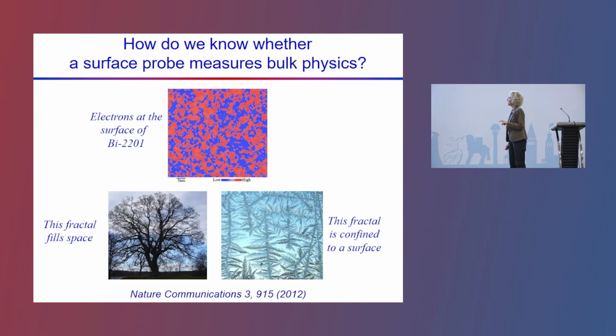I'm particularly excited about this because critical exponents are sensitive to dimension. This is a general method for any surface probe that sees multiscale pattern behavior. If they're seeing critical behavior, if they do this critical exponent analysis, this gives a way for the surface probe data itself to diagnose the dimension of the phenomenon. And this is great. This has been a standard critique of surface probes, that they're only measuring the surface.